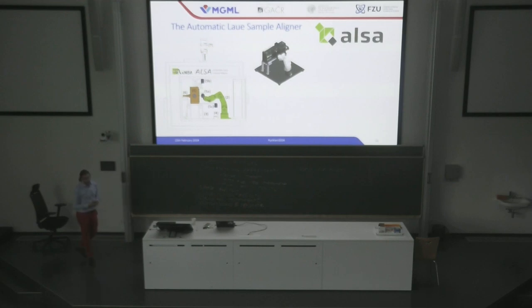So the machine is here. It's a machine we are developing at the faculty. It's very simple. It has a robotic arm and an X-ray source, and it uses the so-called Laue diffraction to figure out the crystallographic axes, and then glue the samples together. So the original idea is very simple. You take the crystal, you put it in the Laue beam, you somehow analyze the results, and you glue it to the plate. Of course, in reality, it's much more complicated.